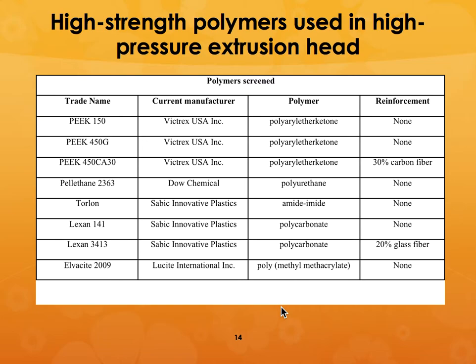So what types of polymers and materials could we use on that high pressure extrusion head? We looked at a number of different types of polyaryl ether ketones, PEEK, which is one of the highest strength thermoplastic engineering polymers. And we also looked at reinforcing them with different kinds of fibers. And Lexan is polycarbonate, so we also looked at reinforcing them with glass fibers. And we at least proved the concept that you could extrude out these materials from the high pressure head and deposit that on a substrate.